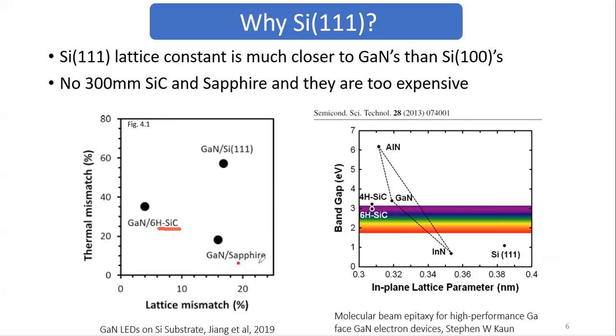But these are pretty good substrates. And then look at the lattice mismatch versus thermal mismatch. You could check, sapphire is pretty good at the thermal mismatch, a smaller thermal mismatch. And silicon carbide, of course, has a very small lattice mismatch to gallium nitride right here. You can use aluminum nitride, of course, but that's another story, right? So for gallium nitride, you should use these materials.